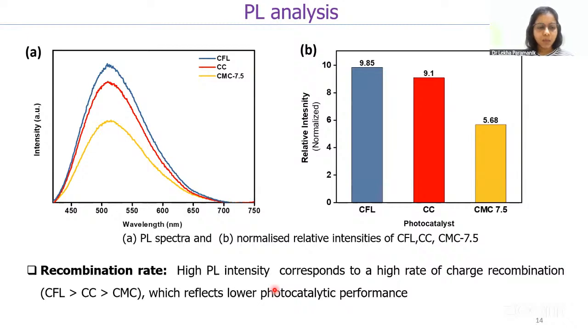This is the PL results of my CFL, CC, and CMC 7.5 samples. From figure A, we can observe the PL spectra, and figure B depicts the normalized relative intensity of the three materials. And from the PL graph, we can say the intensity directly correlates with the charge recombination rate. Higher the PL intensity, higher is the charge recombination, and ultimately it will contribute to a low photocatalytic performance.